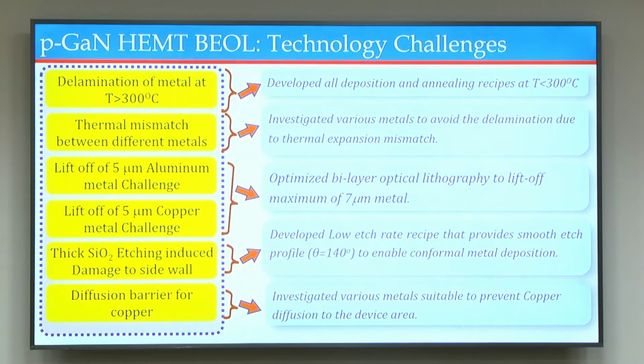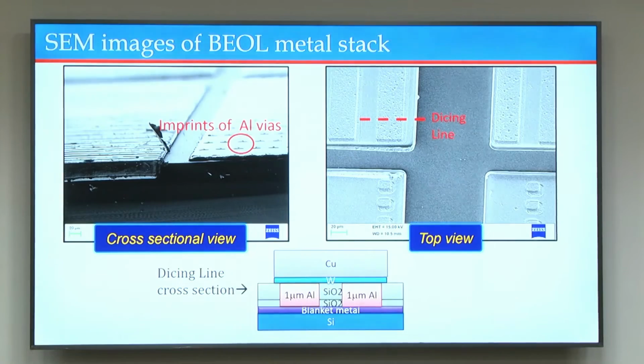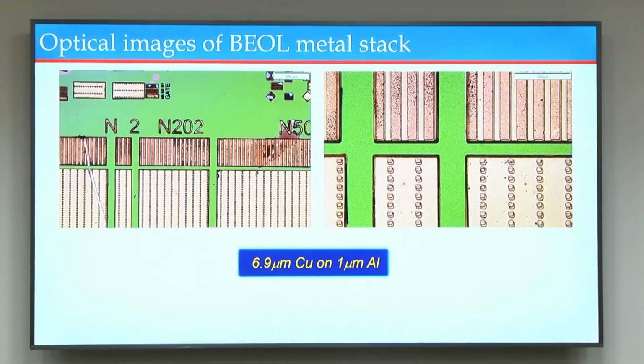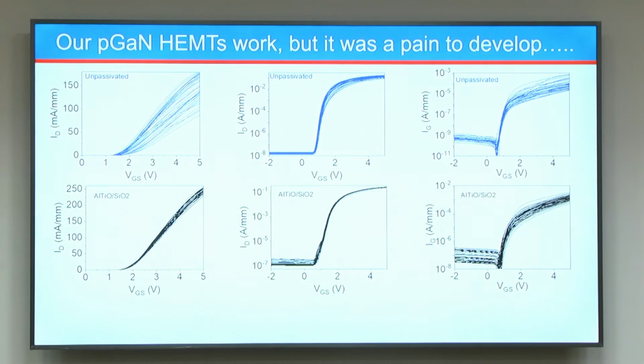We are talking about metal deposited by sputtering techniques, and we are talking about 5 micron aluminum or copper, and then thick oxides as interlayer dielectrics, right. And of course, if you are doing a copper process, then you also have to have the right copper diffusion barrier in your back end of the line. So these are some pictures of our thick metal back end of the line process. This is 7 micron metal, 7 micron copper.